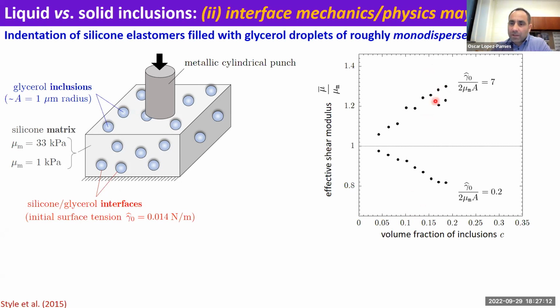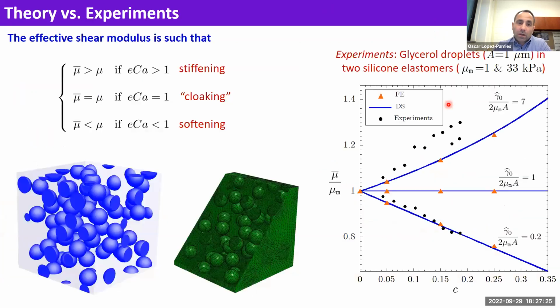So you can end up with a very wide range of behaviors depending on what you do with the surface tension or the initial size of the inclusion, from softening to stiffening, and in fact, to what we call cloaking, right? These are simulations, comparisons with experiments.